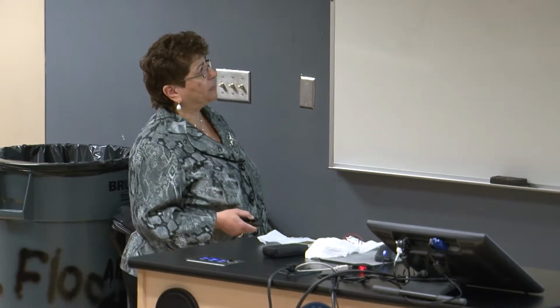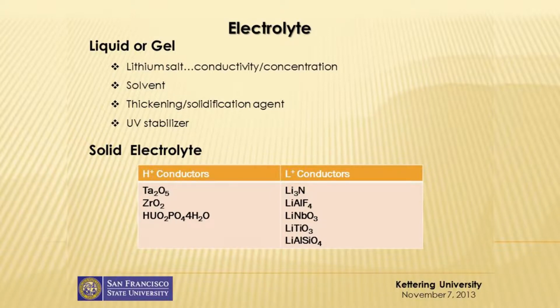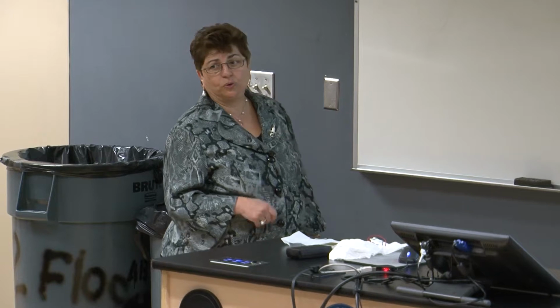Now, one of the most important components of an electrochromic device, where the mobile ions can move easily, inserting and extracting from this material, are electrolytes. Electrolytes can be grouped into two categories, liquid or gel electrolytes. An example of liquid or gel electrolytes is lithium salt. Conductivity and concentration are very important. You need to use a solvent, and you also need to use thickening agents or solidification agents. You need to add a UV stabilizer too if you want to use the liquid or gel electrolytes.